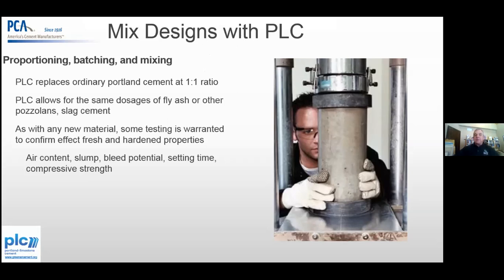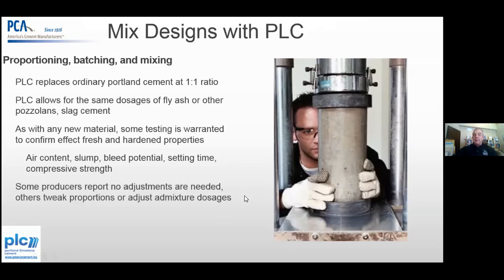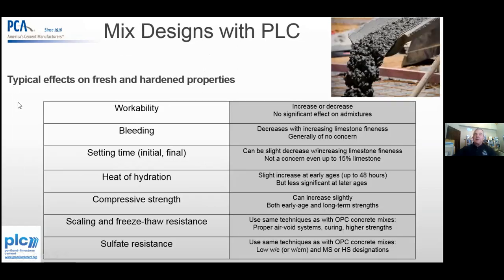Just like with any material, if you change a cement source, or if you change a slag or a fly ash source, you got to make sure you do your testing. You got to test air, slump, bleed, set time, compressive strength to make sure that everything is dialed in. But typically if you're on one source of material and you convert to another source that's PLC, there shouldn't be an issue. Most producers have reported no adjustments. We've heard from some that there might be a slight admixture dosage adjustment for slump, but other than that, it's been kind of a flawless change. But like I said, it took years to do it. We had to build that field exposure site. We had to do a lot of test pavements, and a lot of barrier wall, flatwork, and sidewalks. We did a whole bunch of demonstration projects to convince ourselves that it's the right thing.